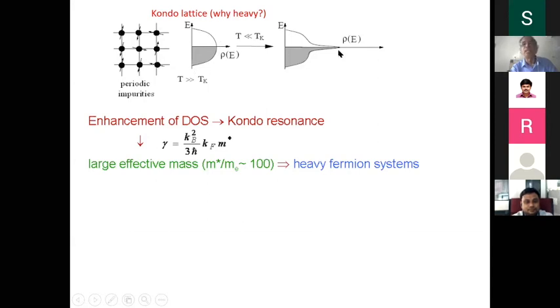Here you have a peak developing. This is coming from 4f hybridization. There is a 4f density here. Normally, you have s electron density, and 4f density here. Therefore, your density goes up, the effective mass goes up. Therefore, the gamma goes up. Gamma is the electronic heat capacity linear term. Therefore, this is the origin of the large effective mass of the Kondo lattices.